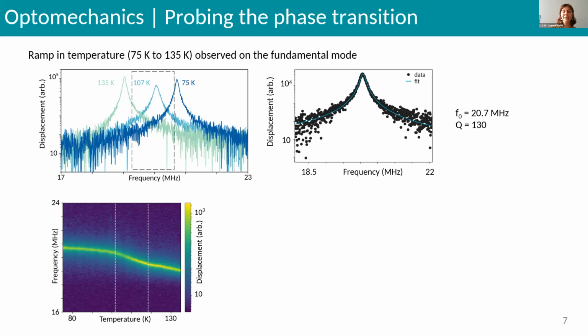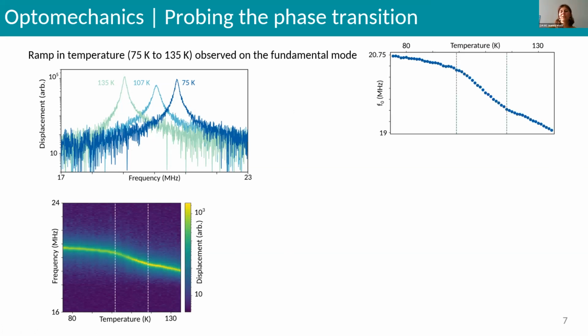To see it more clearly, we can fit the data, extracting the resonance frequency and the quality factor, and then plot the resonance frequency against the temperature. So you have here this break in slope that we can see. So why is it so?